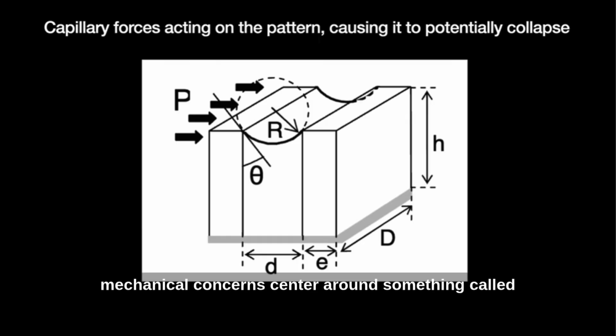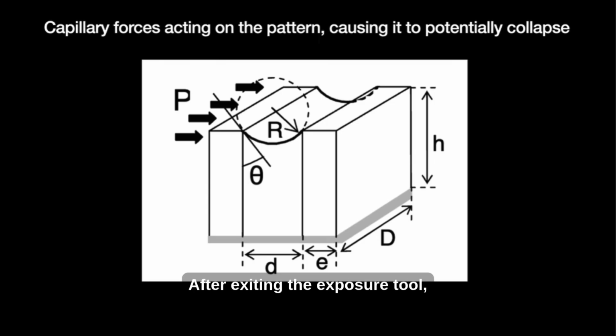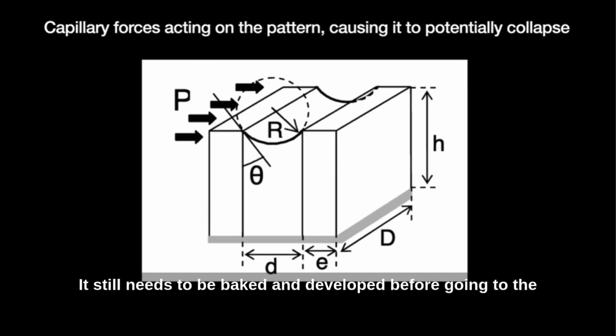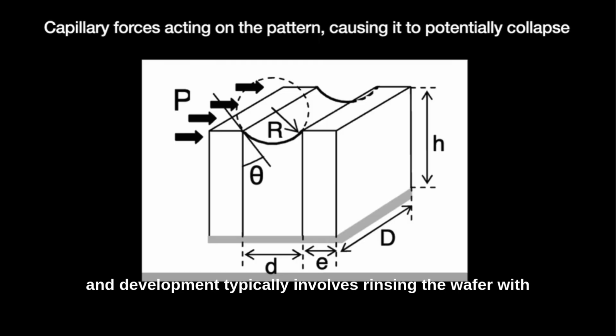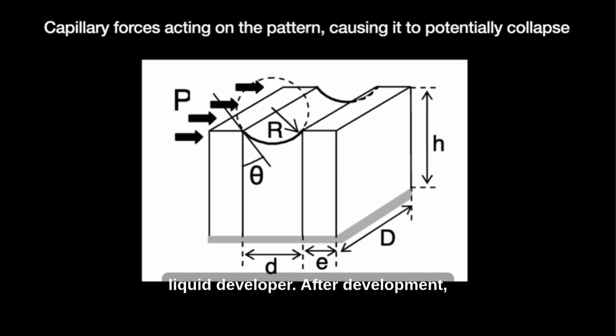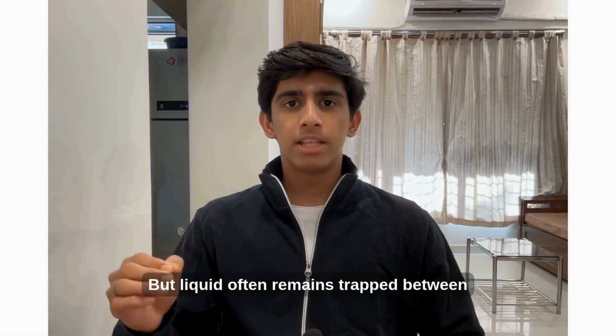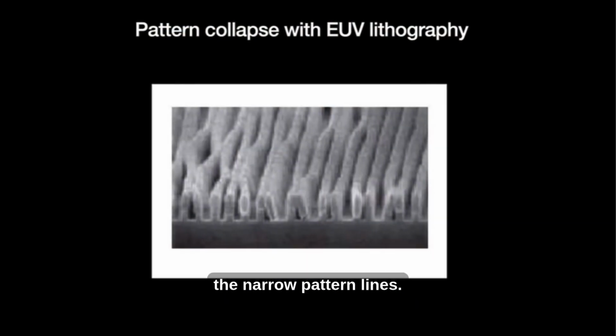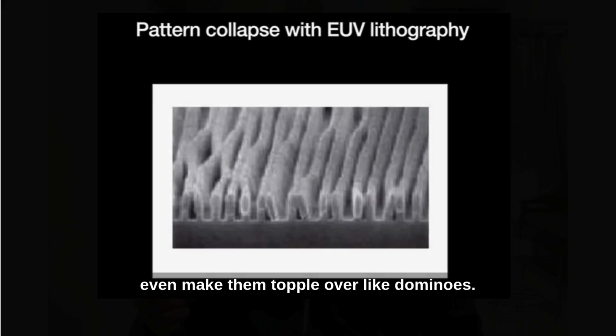The mechanical concerns center around something called pattern collapse, which is exactly what it sounds like. After exiting the exposure tool, the patterned resist layer is quite delicate. It still needs to be baked and developed before going to the etch step, and development typically involves rinsing the wafer with liquid developer. After development, there's a cleaning rinse, followed by drying. But liquid often remains trapped between the narrow pattern lines. The surface tension of this liquid, combined with other mechanical stresses, creates capillary forces that can literally deform the delicate pattern lines or even make them topple over like dominoes.